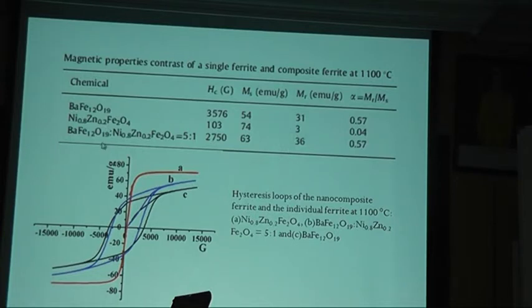But when they combine the two, the mass ratio is 5:1. That means 5 for barium ferrite and 1 for nickel zinc. So the dominant is always the hard ferrite, barium ferrite. They get the remanence ratio increased to 36. We can see this from the hysteresis loop. B is the nanocomposite with the mass ratio 5:1.